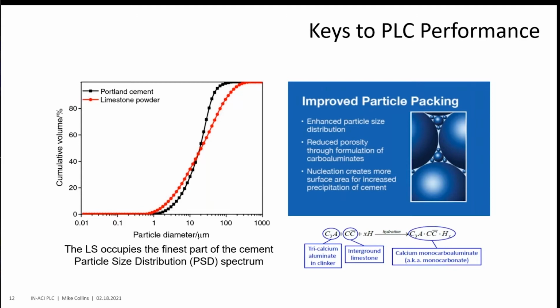The other good thing that happens is because that limestone is so intimately ground and mixed with the material, the cement clinker, that you have nucleation sites. And what that means is that there's some sites where precipitation, these hydration products can kind of latch onto and start to grow a little quicker. And so it helps overall matrix structure within the concrete. Just all really a function, I think, of the particle size distribution and how the limestone being ground with that clinker tends to enhance that.